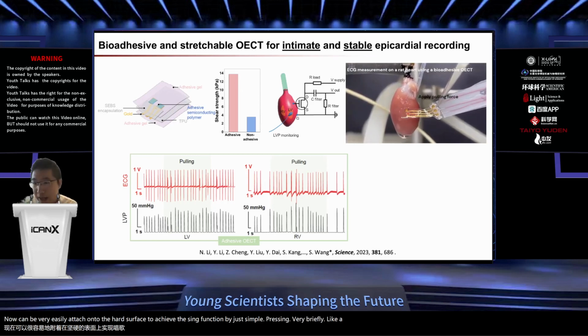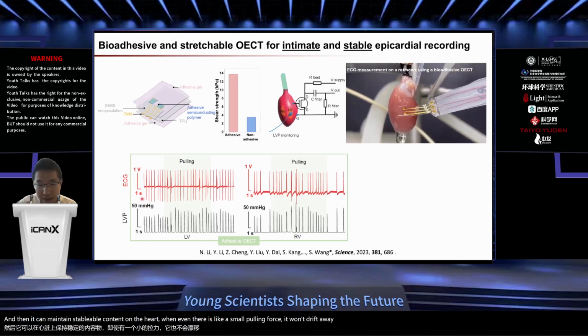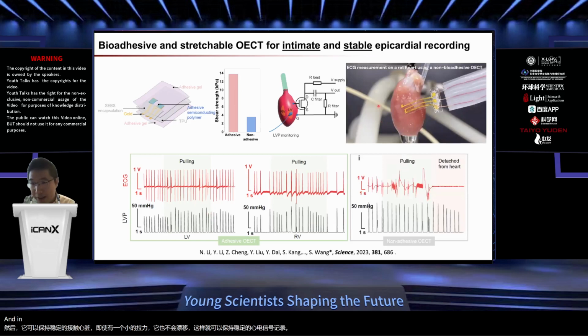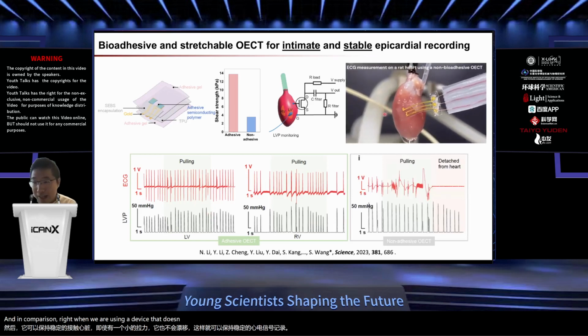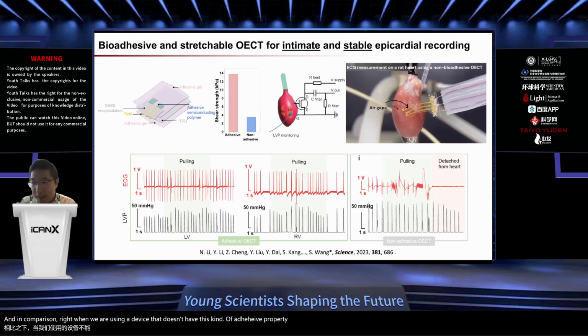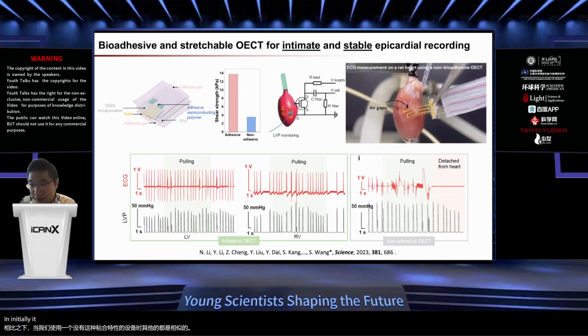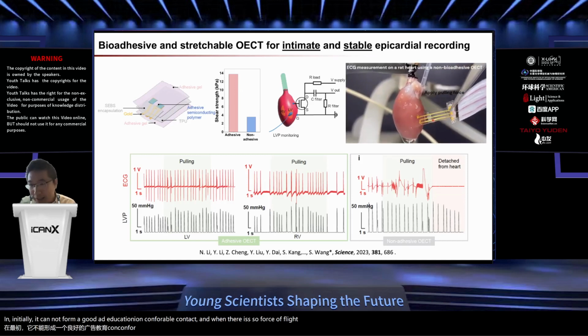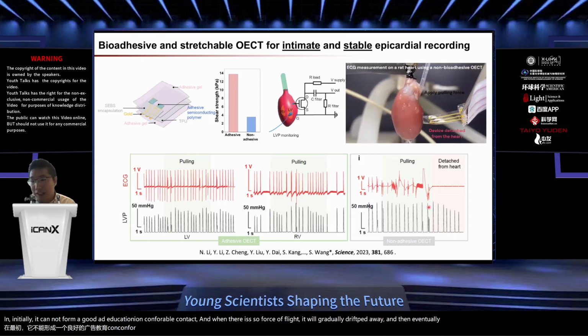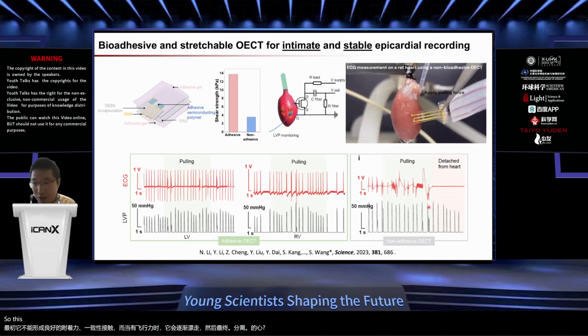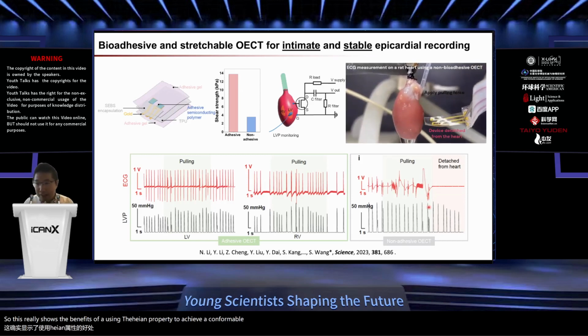It can maintain stable contact on the heart. Even when there is a small pulling force, it won't drift away, and the stable recording of ECG signal can be kept. In comparison, when we use a device that doesn't have this kind of adhesive property, everything else being similar, initially it cannot form a good, conformable contact. And when a force is applied, it will gradually drift away and eventually detach from the heart. So this really shows the benefits of using the adhesion property to achieve the conformable interface and maintain stable contact between the device and the tissue.